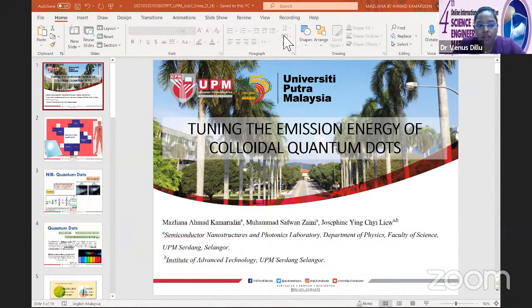About the toxicity. All right. The lead base. Yes, everybody is afraid of lead because of toxicity. What we did at Nottingham University, because actually this work was done when I did my postdoc in UK, was they covered with the liposome, with the protein, to control the toxicity, and also how much lead you put for the bioimaging. So there is a certain level where it becomes toxic, but I didn't study the toxicity. But in order for us to reduce the toxicity, we can use capping. For example, capping with the protein, capping with the silica. That is what I'm trying to do now, capping with the mesoporous nanosilica.